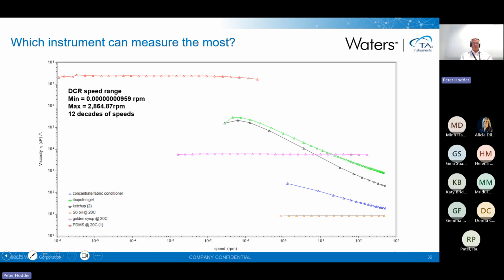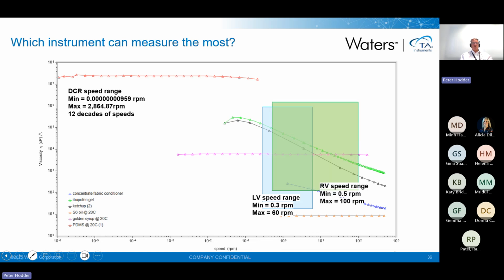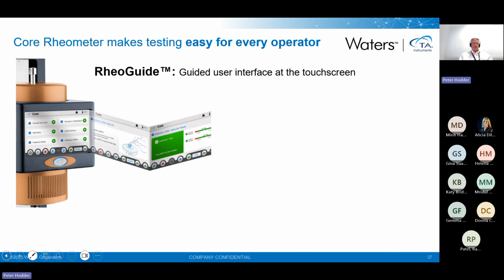So again, the LV will sit in the middle at the high end here. And again, we can start to see something of the shear thinning behavior of the ketchups, etc. We can see more with the RVs, the HAs, and the HBs. But again, we see the fact we're actually struggling to cover the whole range of one sample. So I'm not getting all the information for the ketchup, the gel, or the fabric conditioners. Now, we better talk about the DCR in a bit more detail.